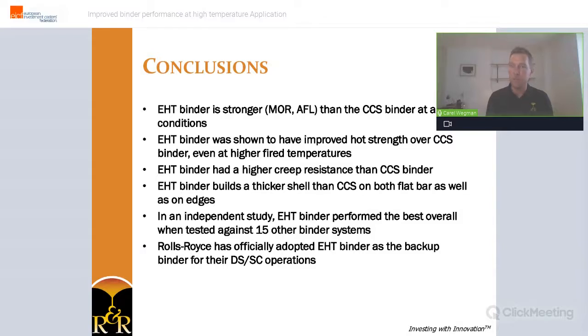Under the same level of stress, EHT binder shells exhibit a stronger creep resistance at both 1200 and 1450 degrees C. EHT slurry builds thicker shell with the same number of coats, not just on flat surfaces, but also on the thin edge. An independent study confirms that EHT binder performs best among 15 other binder systems around that time. EHT has been, in the end, officially adopted as the backup slurry binder for directional solidification and single crystal castings at Rolls-Royce.